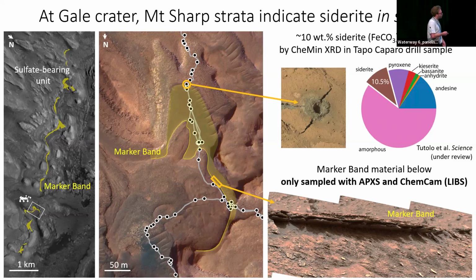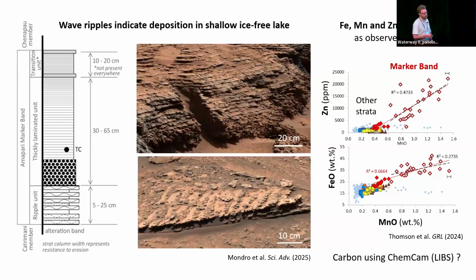We went onto that actual resistant feature here. Unfortunately, it was a little too hard for drilling, although we have lots of chemical data there from APXS and ChemCam. And what came out from that marker band that I want to mention here is that the depositional environment is really clear. You've seen that talk from Claire Mondro about those wave ripples indicating deposition in the shallow lake. They form from the action of waves from the wind. And so they are fossilized there. The whole strata really is a testament to that lake existing at that time and grading here.